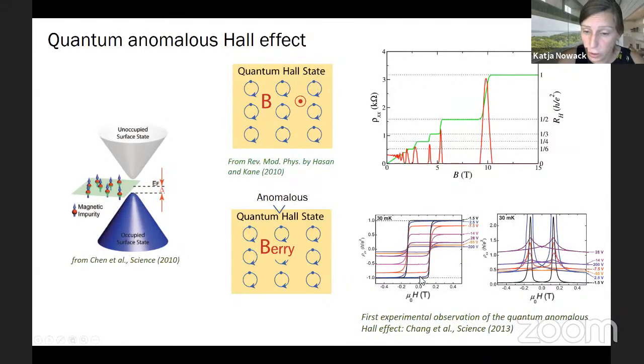And the signature of the quantum anomalous Hall state is also measuring quantized transport coefficients. So here's rho XY, the Hall resistance, and here is the plot of the longitudinal resistance. In the quantum anomalous Hall regime, rho XY becomes quantized, and its value depends on the orientation of the magnetization in your sample, which sets the chirality of these orbits. The quantization persists even at 0 magnetic field, since the magnetization in your sample persists.